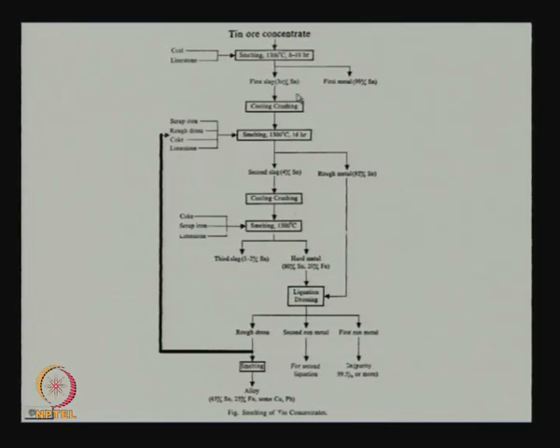Then this slag is not something that we are discarding, it becomes our raw material. This slag will be cooled, crushed, again smelted, and in this smelting process we will again add coke, again we would have limestone and we would have a lot of scrap iron. Why will we add scrap iron? Because iron will dissolve tin and it will help in the reduction process. The aim now is not to produce tin, but to recover tin, and tin will be dissolved in iron.